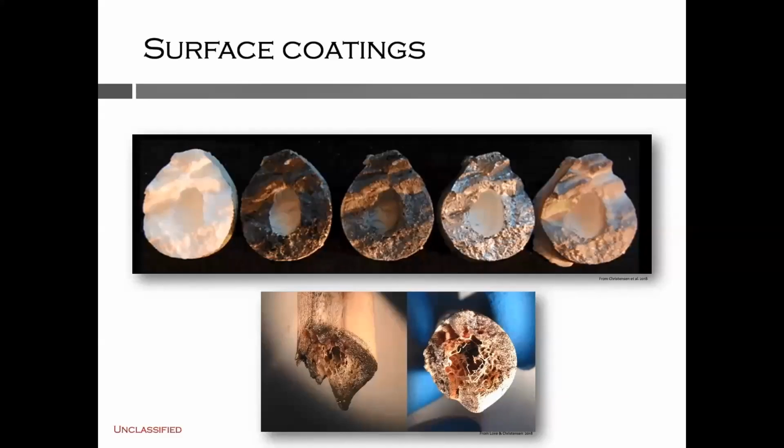Fingerprint powders are convenient because they are reversible as well as inexpensive. Fingerprint powders were used in the case analysis in the bottom two images, which involved a 6-year-old who was struck and killed by a car. In this case, analysis of the fracture surfaces confirmed the direction of crack propagation and impact, which corresponded to soft tissue findings at autopsy.